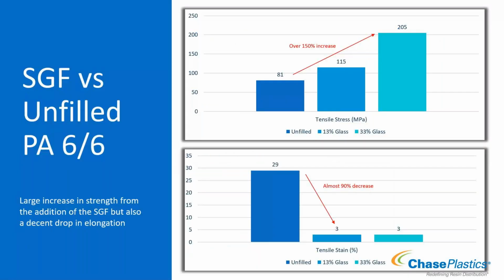Showing what that looks like, you can see a large increase in your strength. This is an unfilled versus a short glass filled PA66. The unfilled in dark blue shows a tensile strength of 81 MPa. When you jump to 33% glass reinforced 6.6, it jumps to 205 - that's a 150% increase. A real good increase in strength performance.